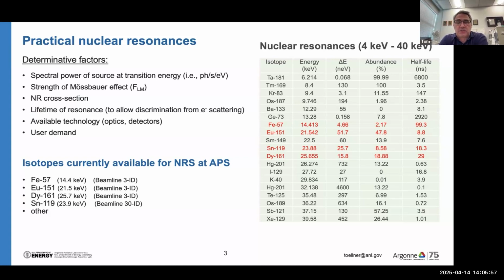The nuclear properties such as cross-section or internal conversion coefficients can affect their suitability. The lifetime of the resonance, I'll show, is the predominant aspect of the resonance that allows us to separate nuclear resonant scattering events from the vast majority of electronic scattering that goes on from a sample. And of course, available technology, optics and detectors: it's easier and generally more developed to produce narrow bandwidth optics for lower energy resonances than it is to do that up at 70, 80 keV. And then in the end, of course, user demand dictates which resonances we focus on.